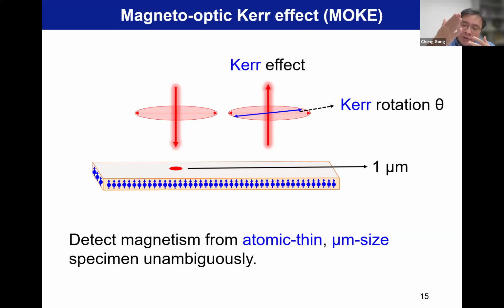some literature called it SMOKE, surface magneto-optical Kerr effect. Anyhow, sometimes people check the Kerr rotation, and sometimes people check the so-called ellipticity. But anyhow, you know, right? One is based on the phase difference between the two circular polarized light upon reflection. The other is based on the reflectance difference of the two circular polarized light. Either way, you can use them to characterize the magnetic property. So this is an area selective, surface sensitive method.